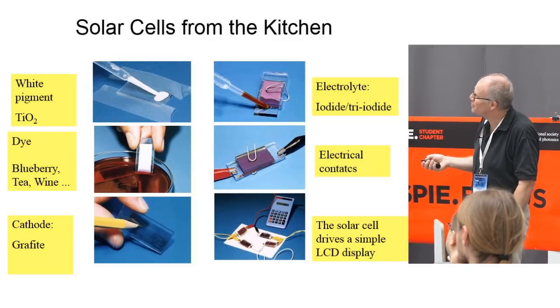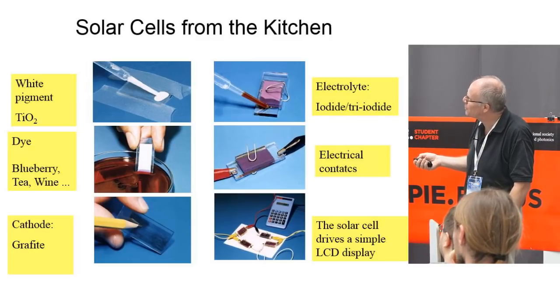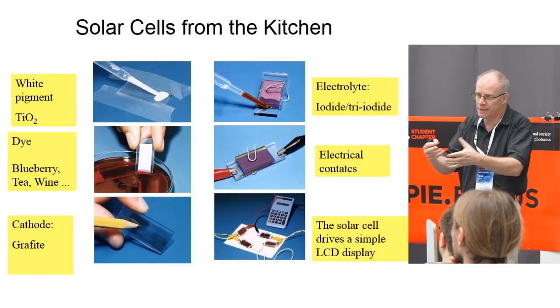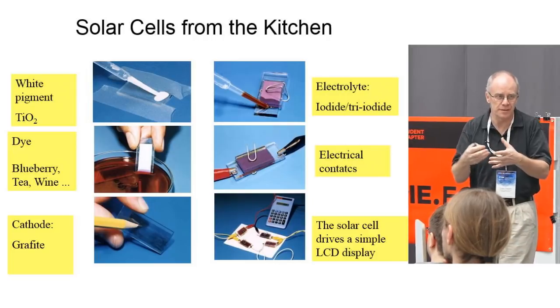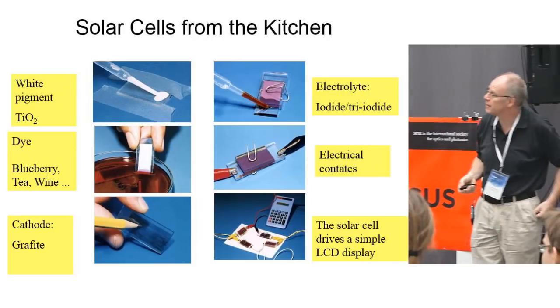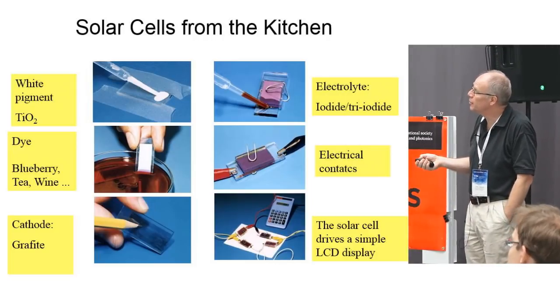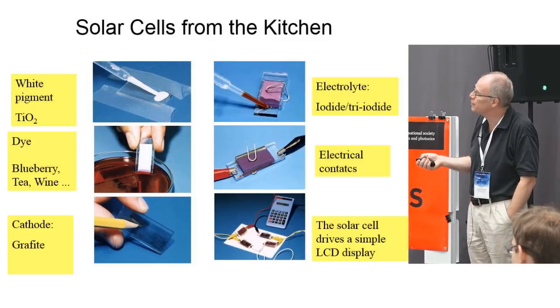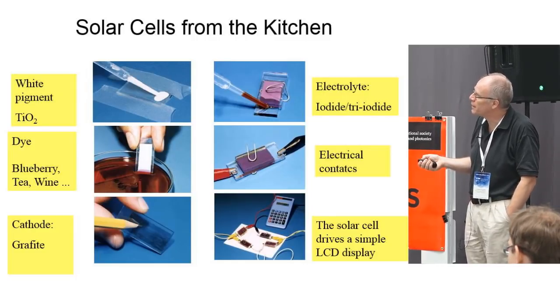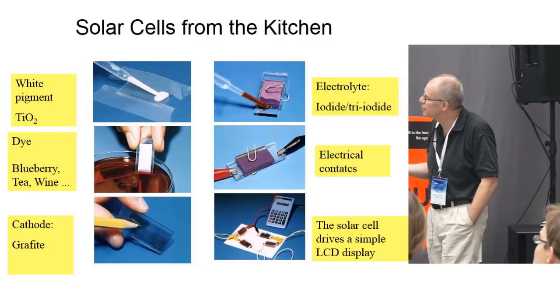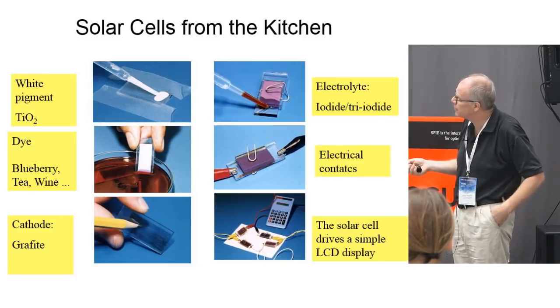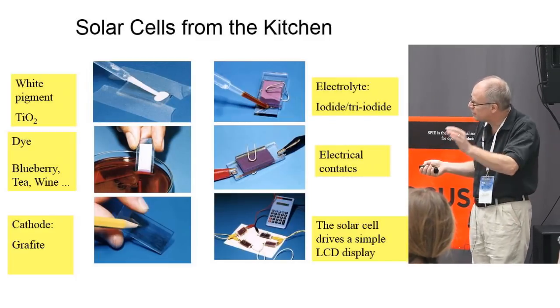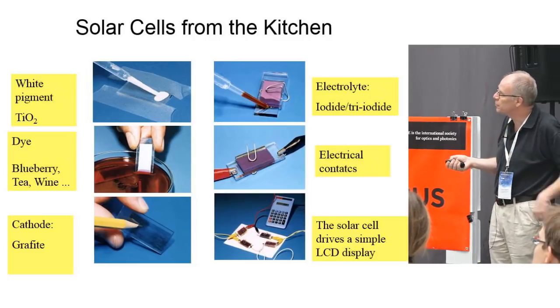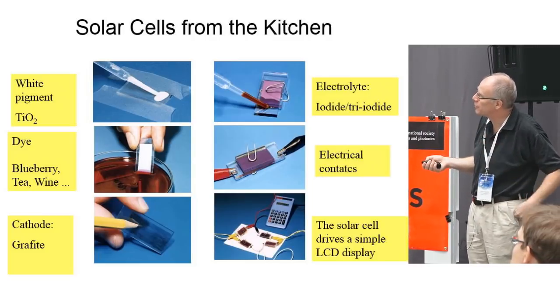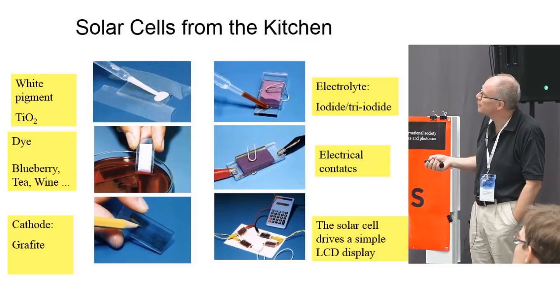But you take this, whatever you take, and then you dip your TiO2 into it, and then you stain the film with this dye. And that's your dye-sensitization. That's the anode, the photoanode, the minus, let's say. You need a plus electrode, the cathode, and then you take graphite from your pencil. So you take the other piece of glass and just write with the pencil, and you have a carbon counter electrode, as we call it.